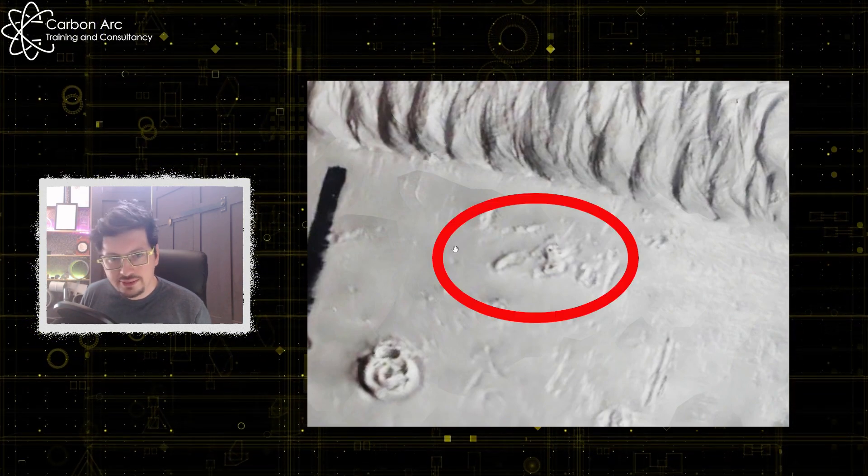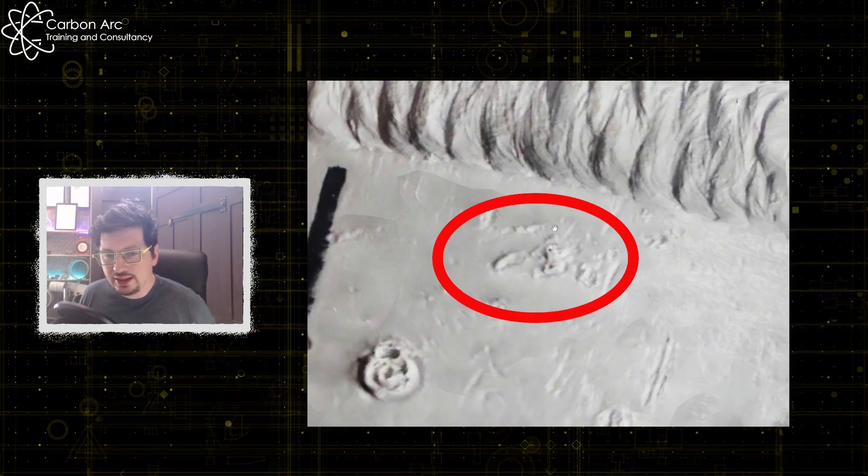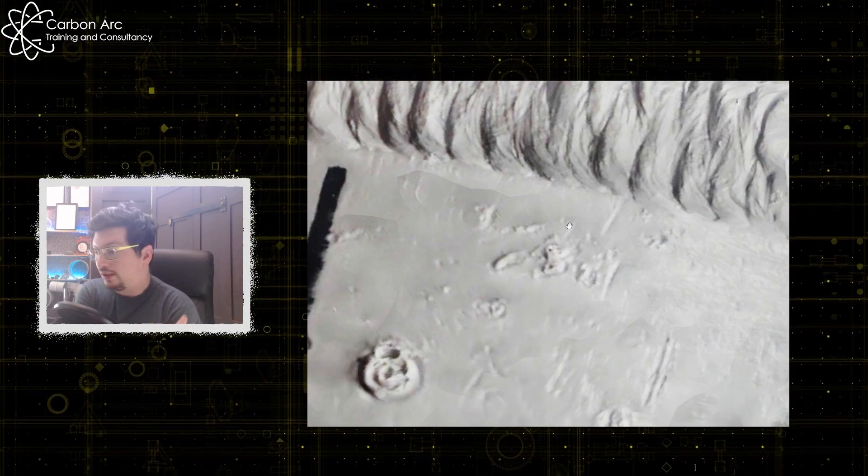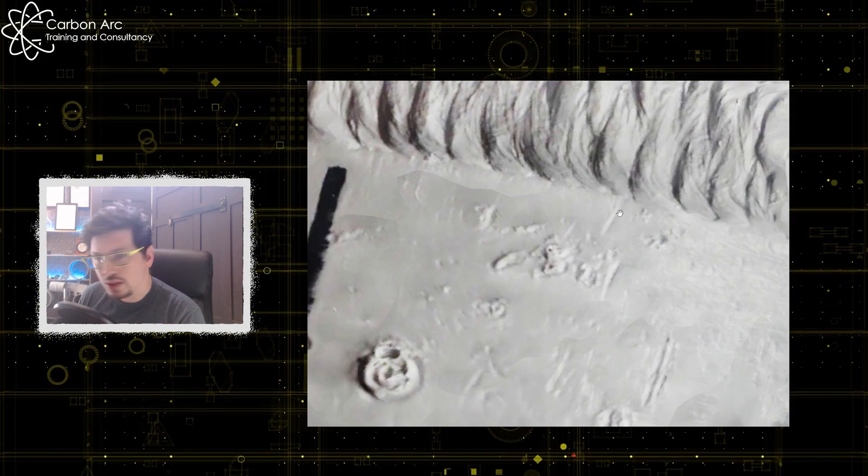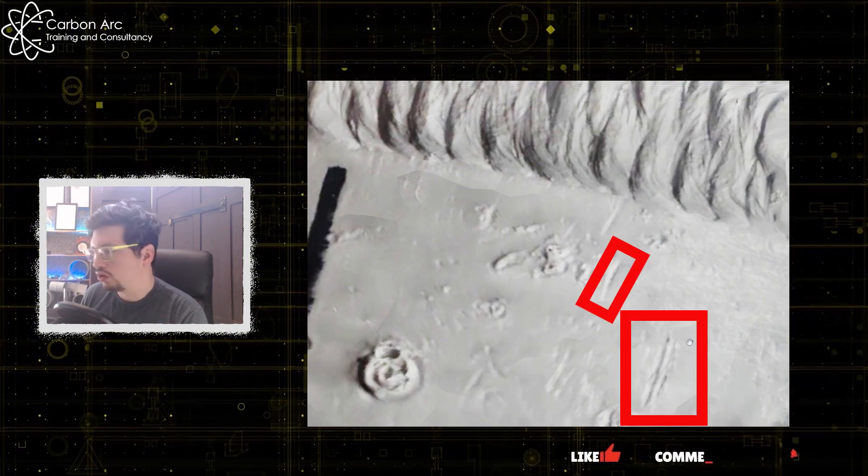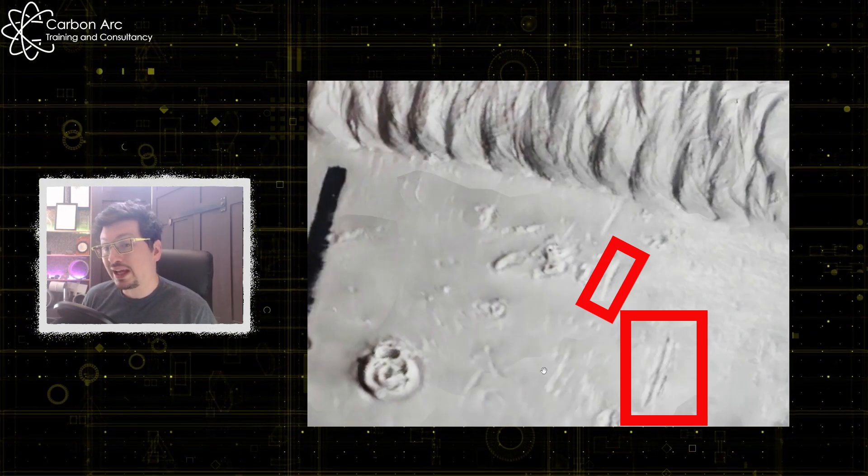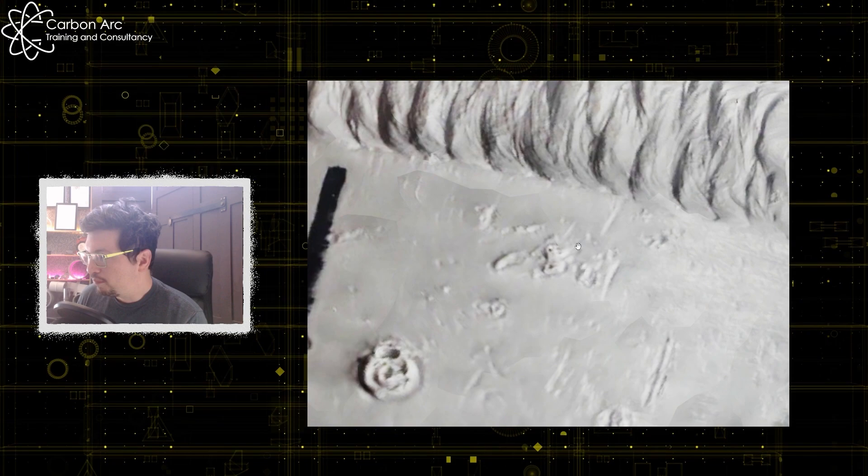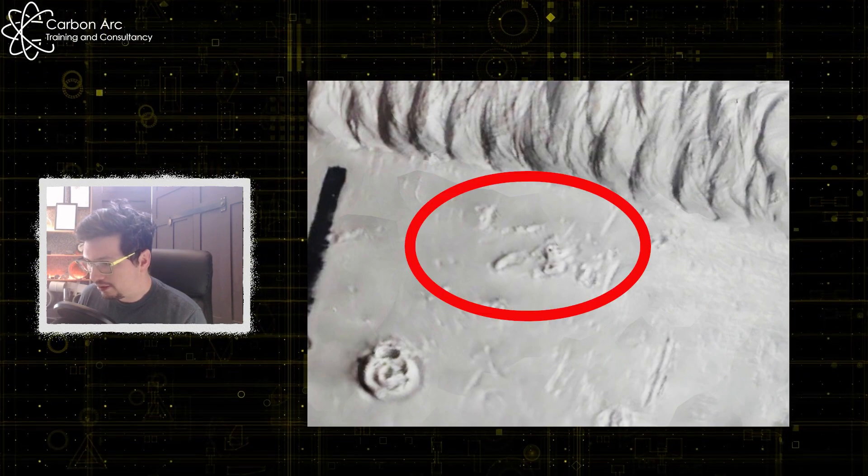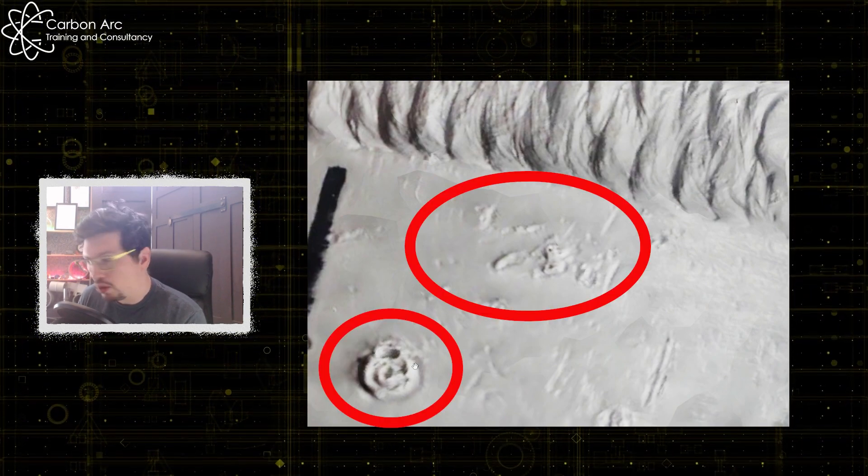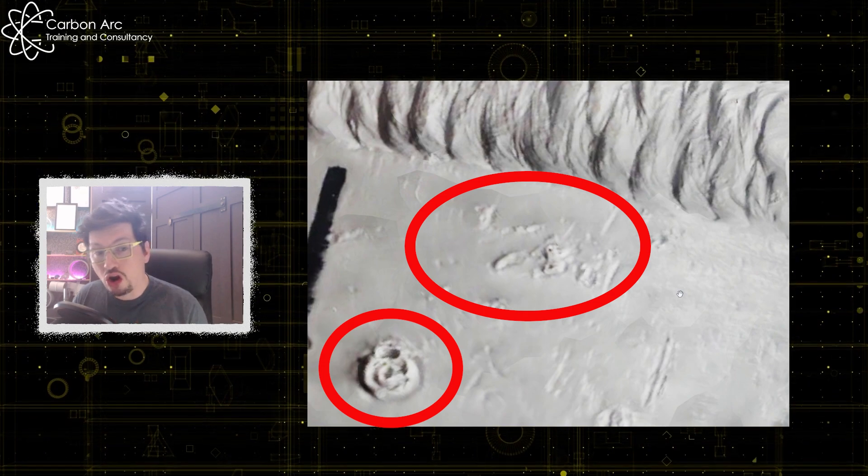So what we've got in this entire area is a couple of different things happening. You can see we have some long longitudinal scratches which would be mechanical damage. But definitely in this area and potentially here at the bottom, we're looking at an arc strike.